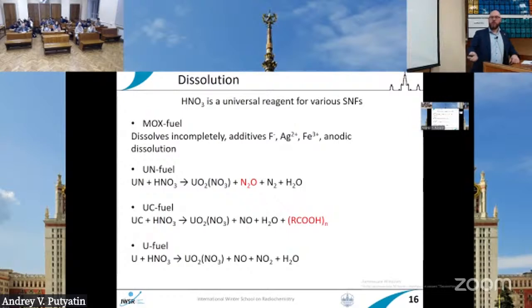Nitride fuel is very easy to dissolve again if we are talking about the uranium, but there is a formation of nitrogen +1 oxide, and it is an oxidizing agent, not like oxygen, but it can be used as oxygen, so it can be a dangerous flammable situation with this oxide. So there is additional treatment of gases to avoid the formation of this oxide in the air. Carbide fuel. The problem with the carbide fuel is the formation of different organic compounds with the dissolution in nitric acid. So for further reprocessing, we need to remove these parts from the solution.